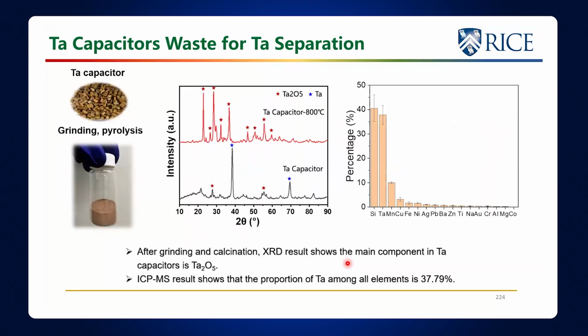Then we got tantalum capacitor waste. All of this waste we get from eBay. It looks sort of like little pieces of candy, these tantalum capacitors. So you grind it up, and then you calcine it. That'll burn away the plastic, and you get the tantalum capacitor. You see tantalum there, and then when you oxidize it, you burn away the plastic. You get the tantalum oxide.